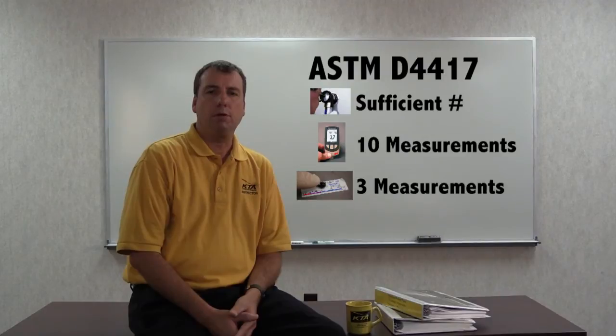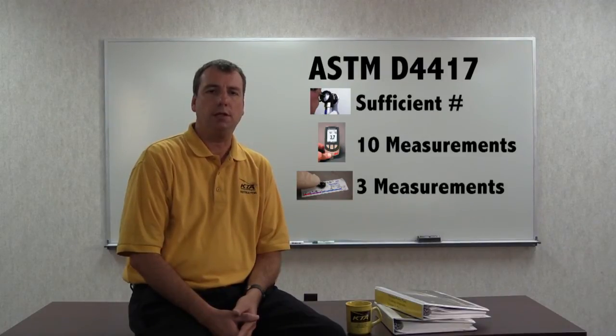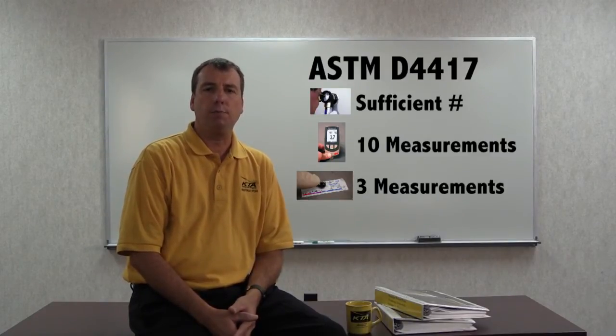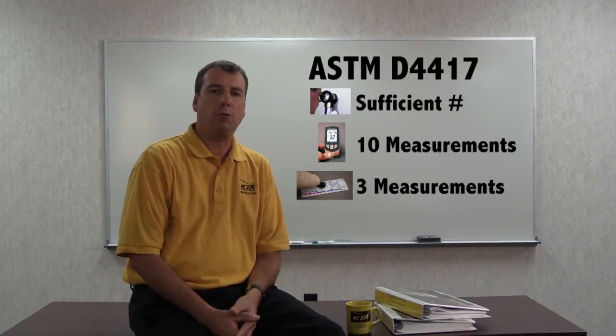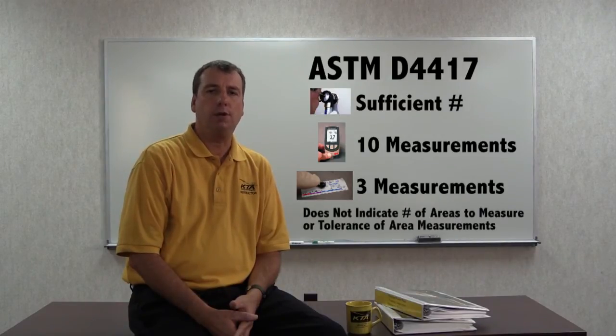For the Visual Comparator method, ASTM states that a sufficient number of measurements should be obtained in each area. For the depth micrometer method, ASTM requires 10 measurements in each area, and for the replica tape method, ASTM requires 3 measurements in each area. The ASTM standard indicates the number of readings to take in each area for each of these methods, but does not indicate the number of areas to measure on a structure and does not address the tolerance of the area measurements.